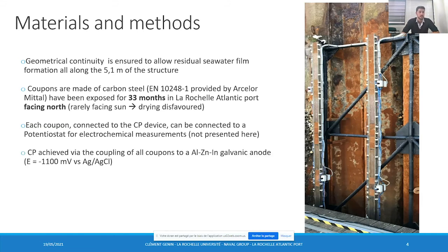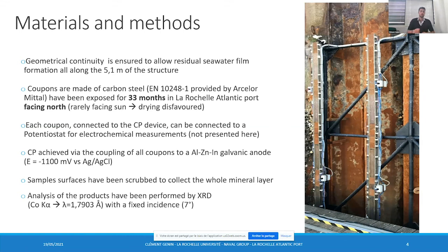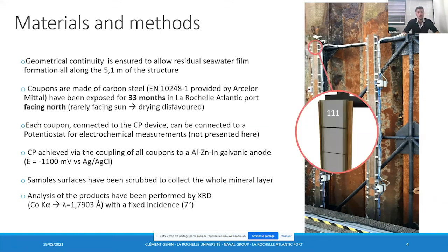As I said before, this is a galvanic cathodic protection device using an aluminum-zinc-indium galvanic anode. To collect the results, the sample surfaces were scrubbed to collect the whole mineral layer, which was then crushed to perform XRD analysis. The samples are named as follows: 111 because this is the first column of the first section and the first sample. The following one is the 112, and so on and so forth.